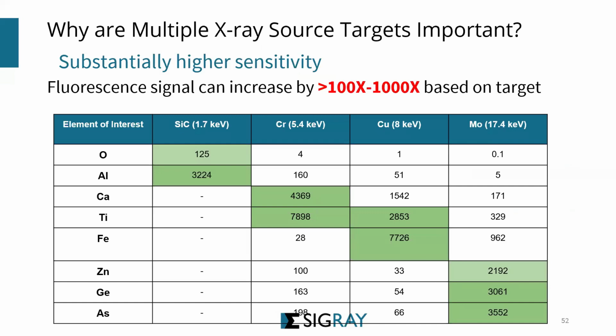For instance, if I'm interested in aluminum, and I use the wavelength or the energy of a molybdenum, this is the fluorescence cross-section, or you may convert that into the count rate. Let's say you may have only 5 counts, but if I shift my target of the X-ray tube to copper, or 8 keV, we got 10 times improvement, but it's still very miserable, because 51 counts is not going to do you a lot of good.